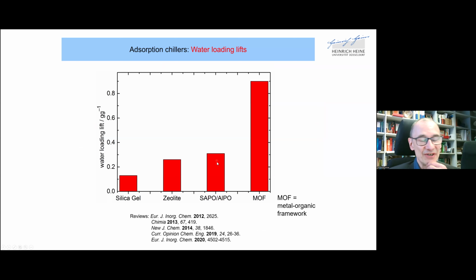So now I come to the question which I wanted to pose already, namely, why should MOFs be of interest in this technology if this technology already works with silica gel and zeolite? And the answer to the question is given here. Silica gel and zeolite are not really very porous. Their uptake capacity of water per gram of material is below 0.2 gram per gram for silica gel and 0.3 gram per gram for zeolite. And understandably, the more water goes into an amount of adsorbent per cycle, the more efficiently the cycle can be run. And MOFs, as I pointed out in the very beginning, have a higher porosity or higher pore volume than many of the classical porous materials.